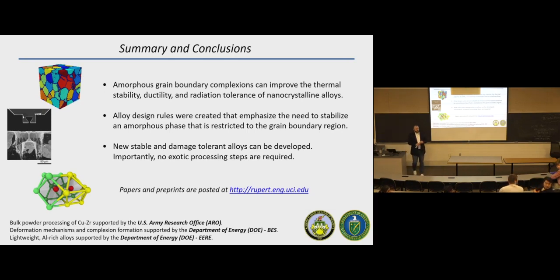You said that at some material mixtures, you're able to produce different thickness of amorphous layers. Have you noticed that there's any diminishing returns depending on the thickness of the amorphous layers? So there would be if you go to the extreme. If you were to make it 50 nanometers thick, you would end up having a material which is mostly amorphous material, and it probably would be pretty brittle.